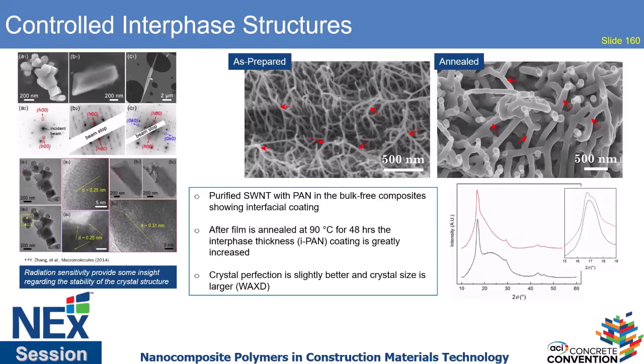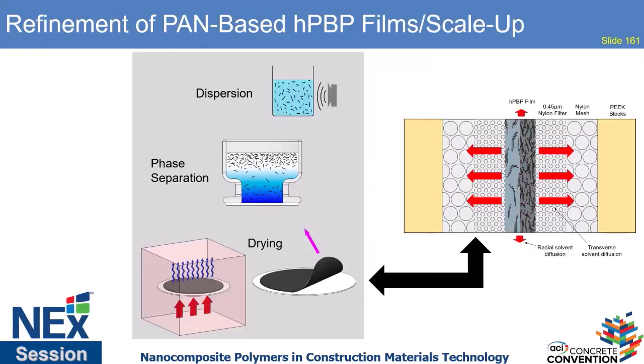We studied crystallization of the polymer. We studied annealing. And in all these cases, again, we keep getting nice structures of polymer around these nanomaterials. So how could we then couple that to what we're doing in the phase separation? Well, with this system now, when we do our dispersion and we use phase separation, we're collecting essentially a paste, a polymer that is very well uniform and interacting with a certain subset of nanotubes, and we can remove all of the nanotubes or that nanotube-rich layer that we don't want, and we can create films or non-woven structures from that and study them.